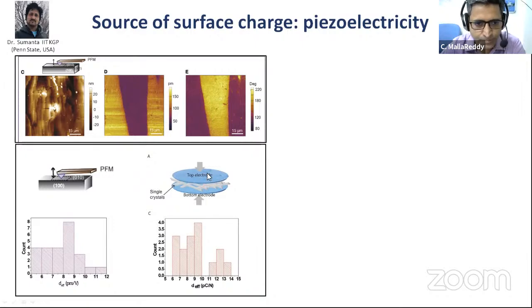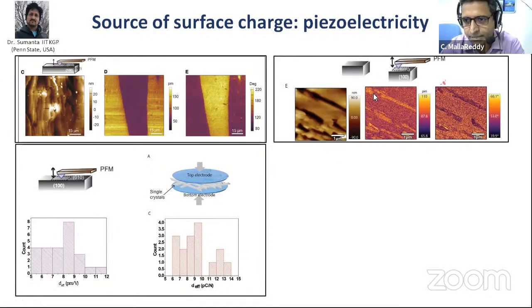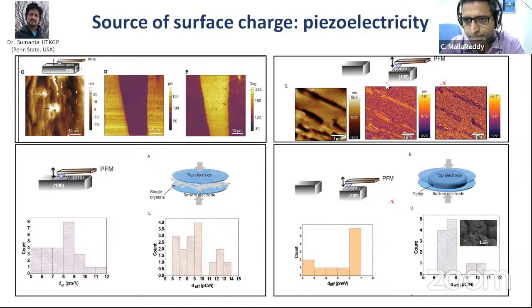Then we have also done the piezometry measurements with the bulk crystals, and we again found that it is a nice piezoelectric material. And then we have done different measurements on the broken crystals. When we did the experiments on broken crystals, we see a slightly lower piezoelectric response. That means there is some fatigue in the crystals.